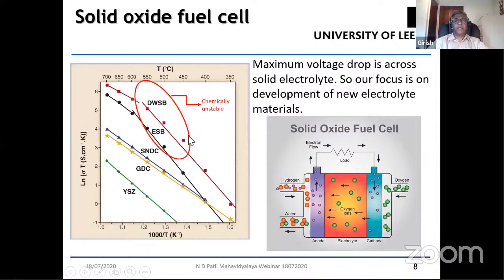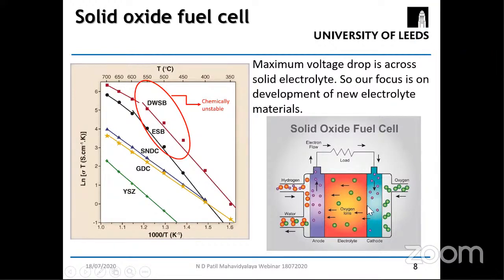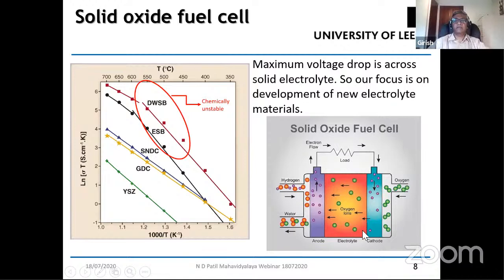So much of the research has gone into using bismuth oxide as the electrolyte at the cathode interface, where the oxygen potential is higher, and you have a graded electrolyte being used, where it goes from bismuth oxide rich to yttria or gadolinium doped ceria rich electrolyte materials.